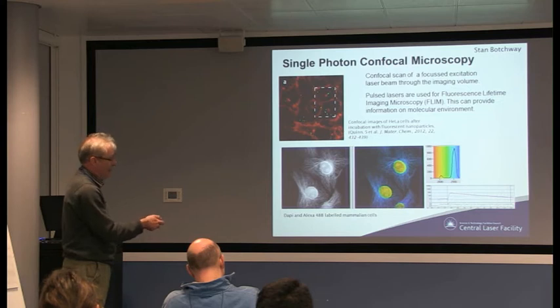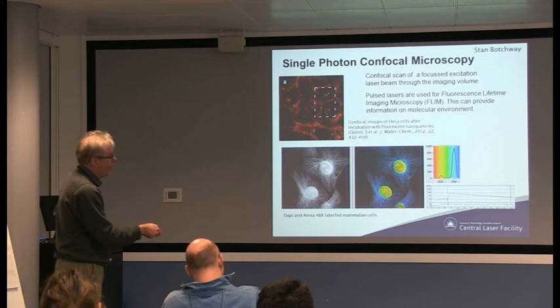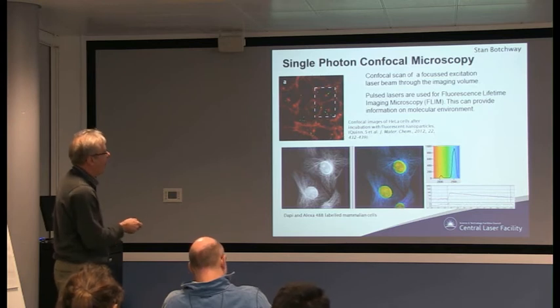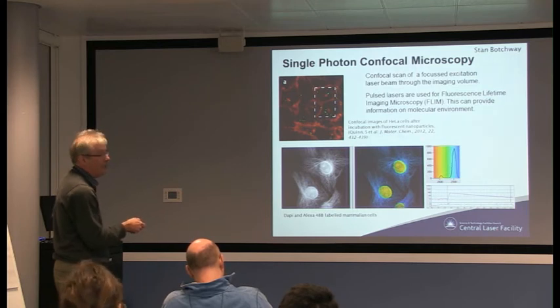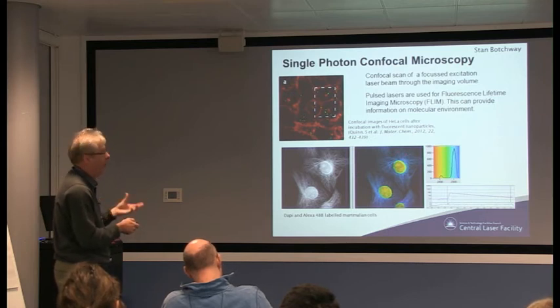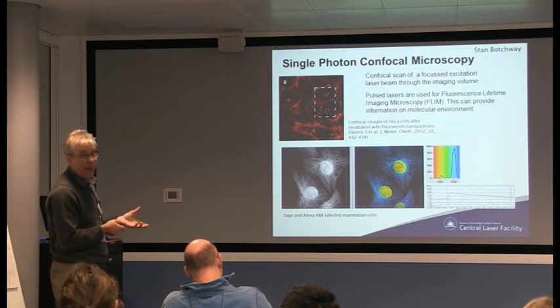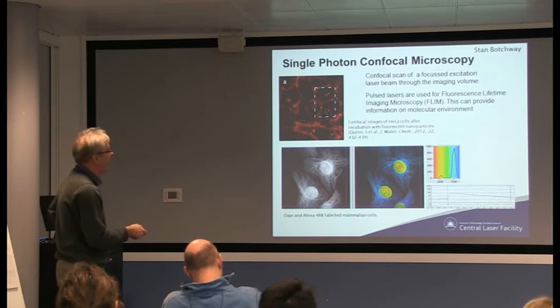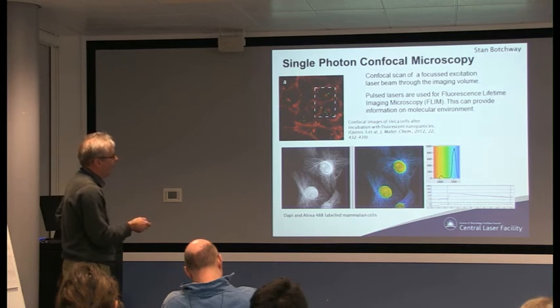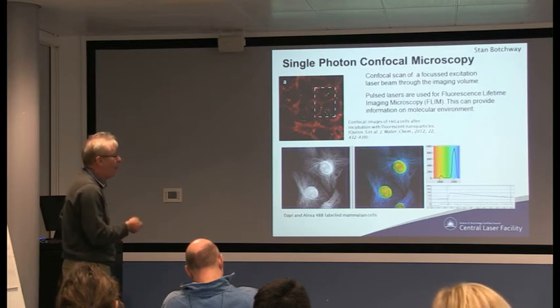In this particular case, you'd be looking at lifetimes of 2,000 to 2,500 picoseconds. That's actually quite interesting, because if you look at this lifetime, you can tell things about the molecular environment. The fluorophore might be bound to something in the structure, maybe the fluorophore's reacting, or the structure to which it's bound is reacting, or maybe there's a different viscosity or pH which is changing the way the fluorophore's behaving. So you can get very detailed information, not just on where the fluorescent signal is, but actually what that fluorophore is doing and the properties around it.